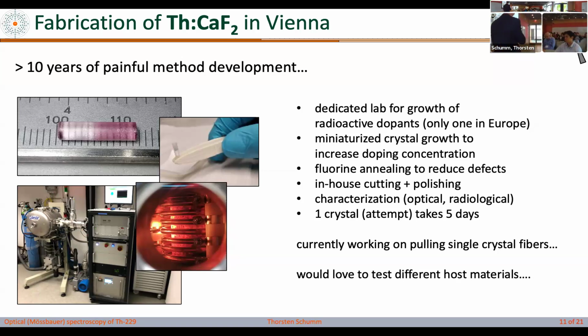By controlling the temperature very precisely, we drive this interface through the crystal at 1 millimeter per 5 hours. So it takes several days to grow a crystal, although it is really very, very tiny. That determines the optical quality, and a lot of properties crucially depend on how carefully you can do this. So it's not science, it's almost alchemy. It's a little bit magic, but very painful to learn.